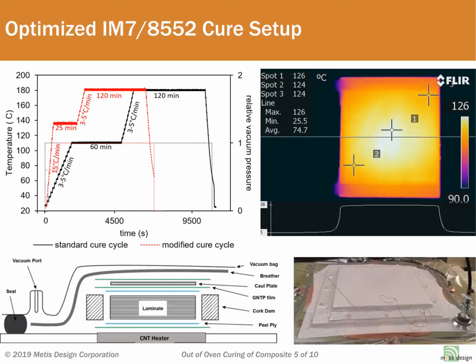However, in an autoclave, considerable time is wasted in heating the air and heating the metal tool, and much more time must be spent dwelling at the gel temperature, where most of the air is removed, to make sure the laminate has isothermed at that temperature before further increasing the temperature to allow matrix cross-linking to start to occur.